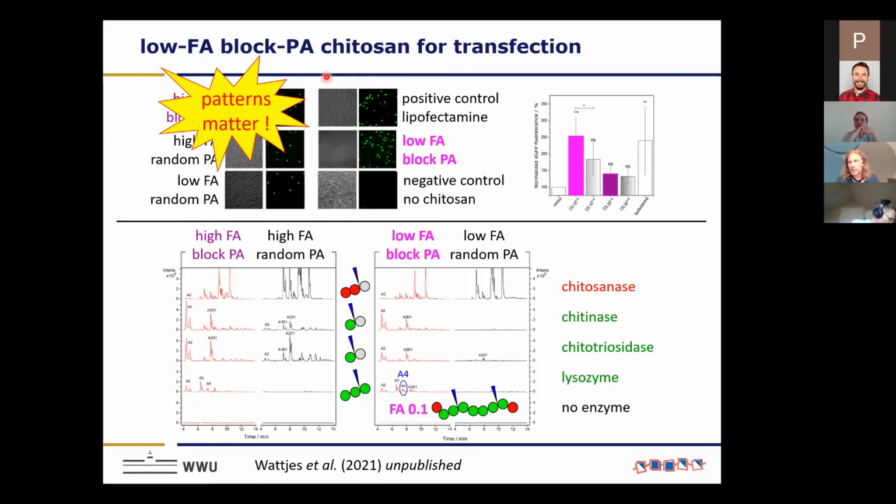I think it's both. If you look at this, in gray we have the chemically produced ones. So even with the chemically produced chitosans, a fraction of acetylation of 0.3 is less effective than 0.1. So with a low fraction of acetylation, the more positive charges are better, most likely because they are better taken up by endocytosis into the cell.